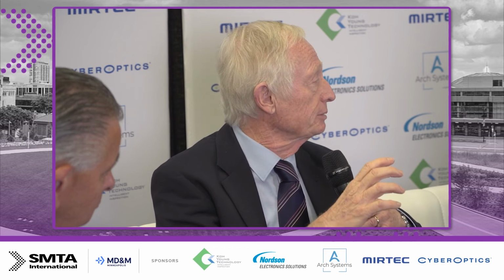Yeah. So I think the industry is drifting, interesting I use the word drifting, towards homogeneous joints, where you have an LTS ball and an LTS paste. And I say drift because one of the issues that we find with the hybrid joints is that after thermal cycling, you find the solder ball has moved. It's actually drifted away. Right. And there's a whole lot of reasons why that is. But these are all complications. Look, it's tough enough as it is without the solder balls moving around. I don't think the hybrid joint will make it to the next stage of low temperature soldering.